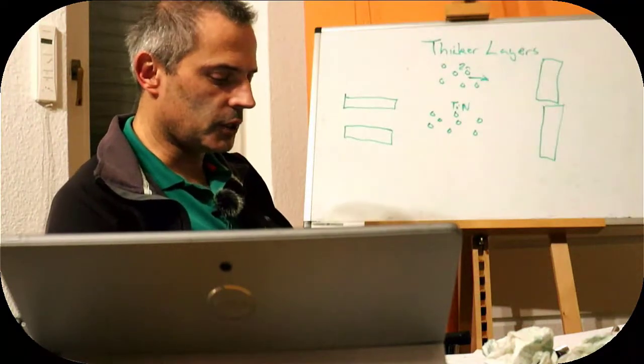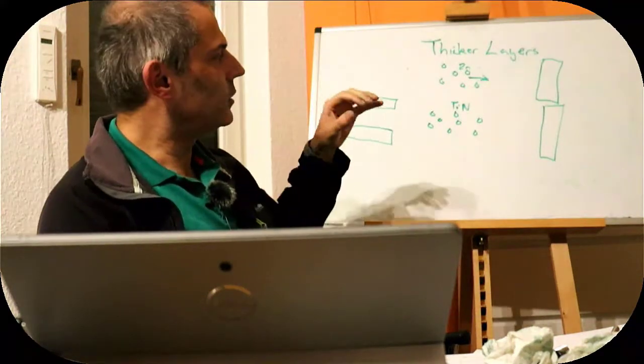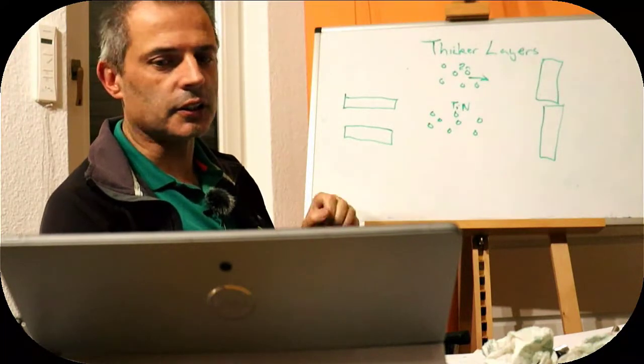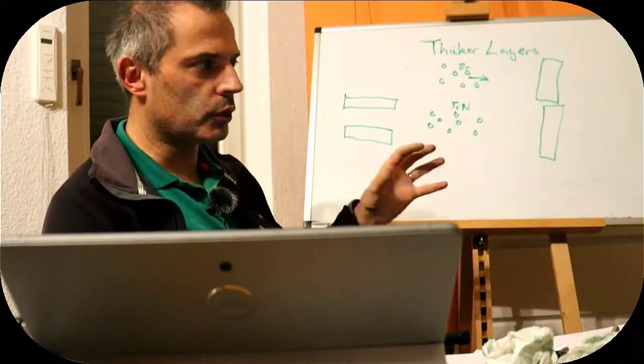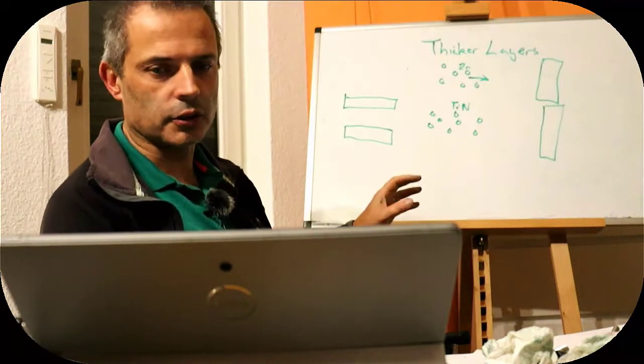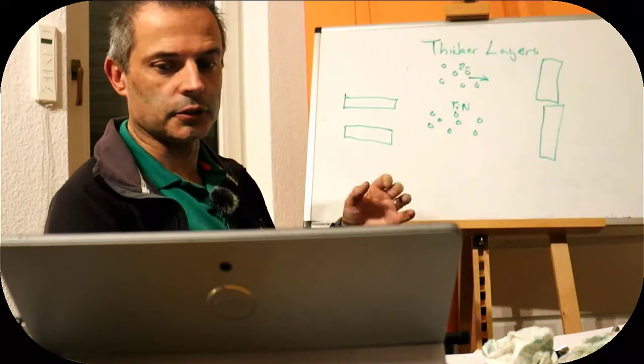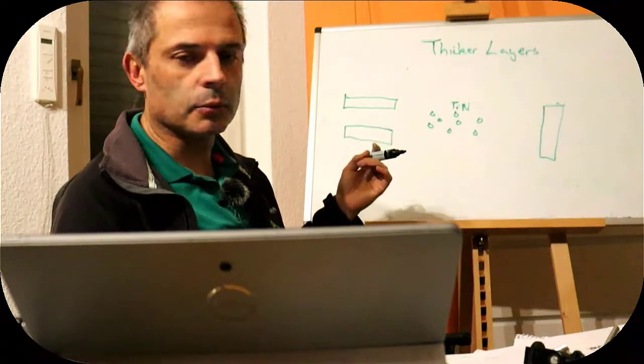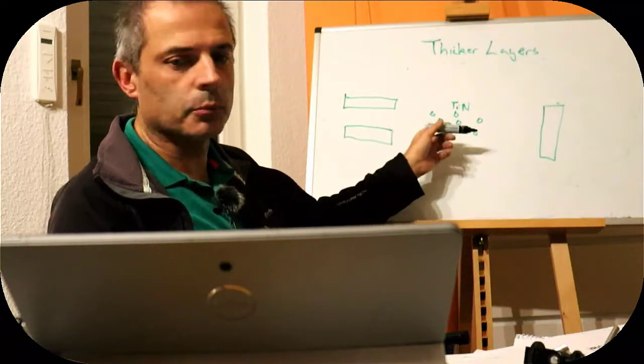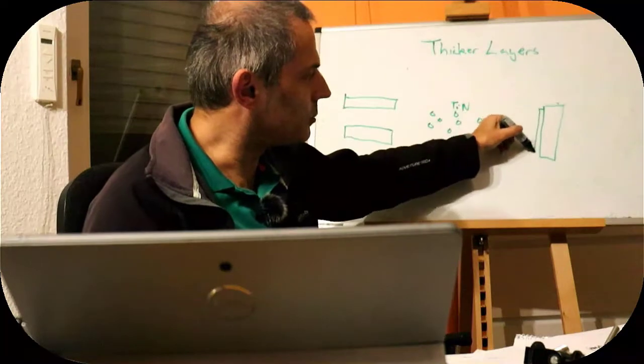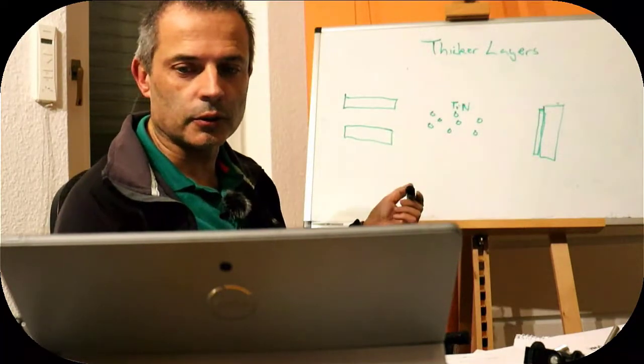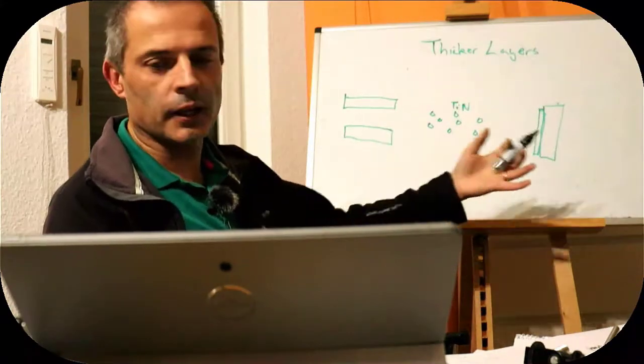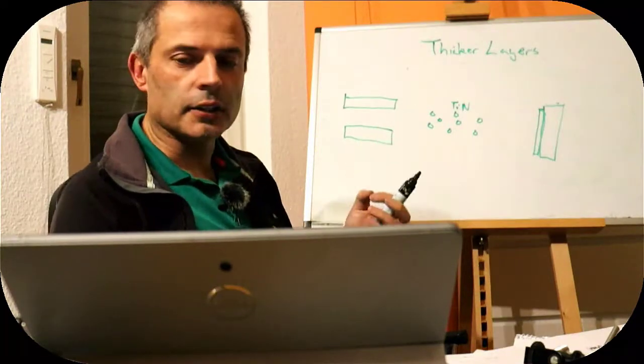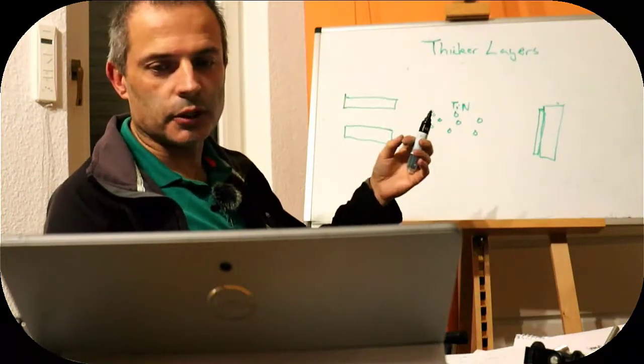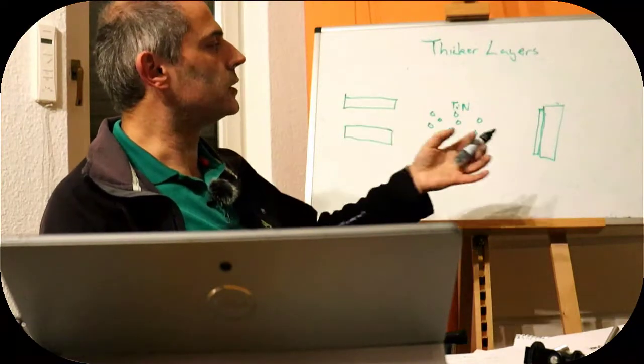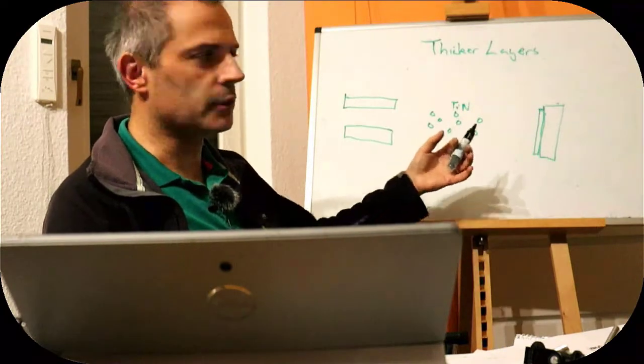But let us do the whole thing using the titanium nitride as an example, so that we can do the process in general, and then all of the variants of it are simplifications. So this is our process. We want titanium nitride particles to form a titanium nitride layer of some kind on the surface of our substrate, and it will not be hard enough to take titanium nitride particles whacking into it, but it's heat resistant enough that it can take them when they're very hot.